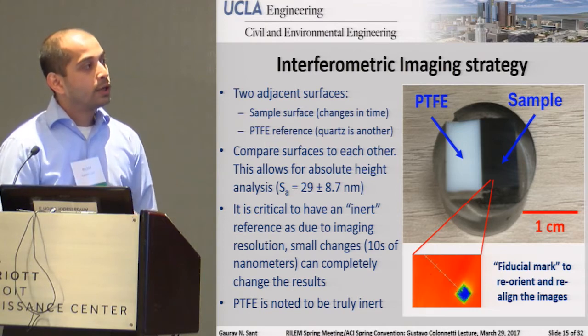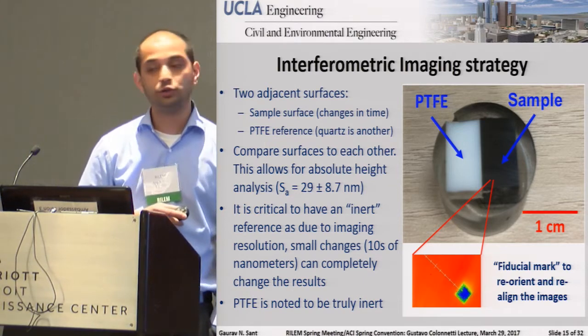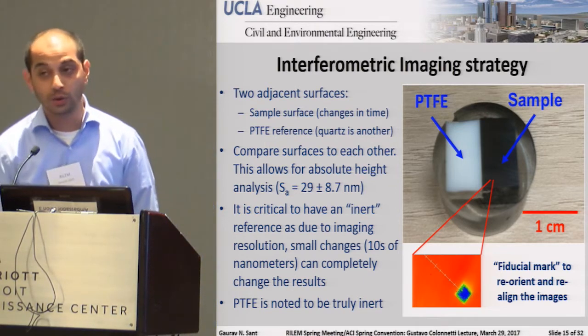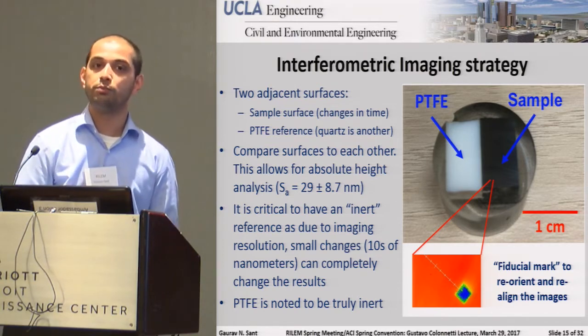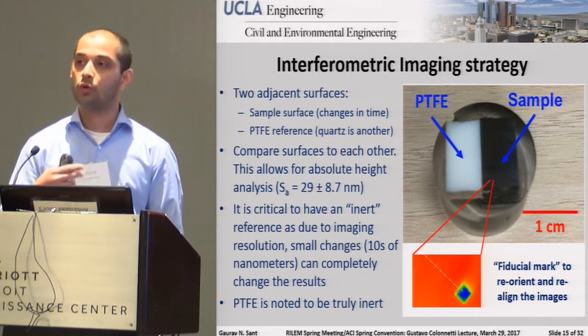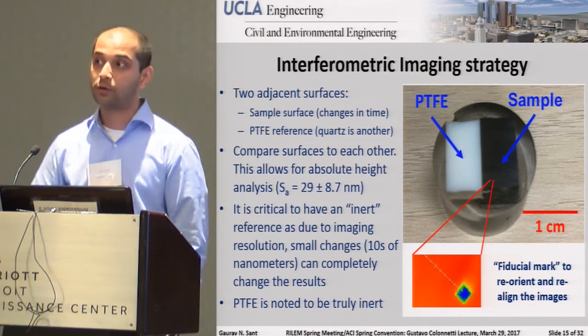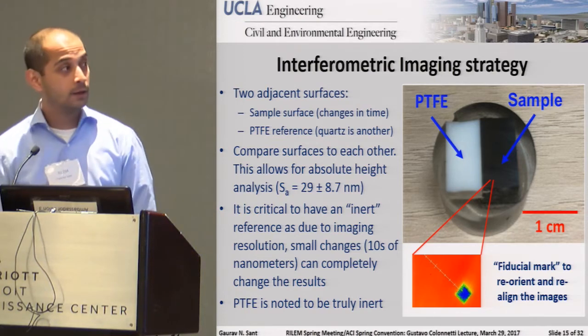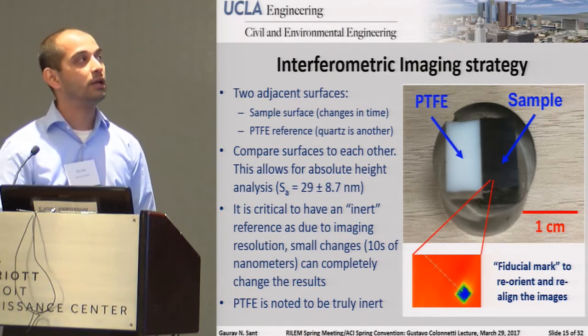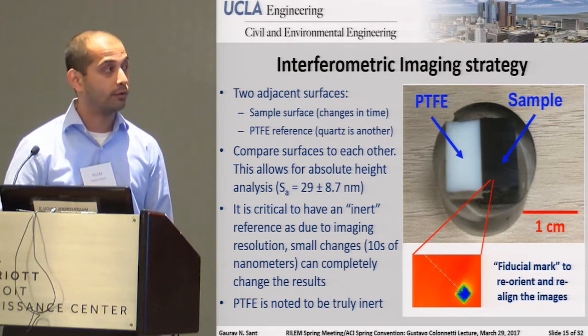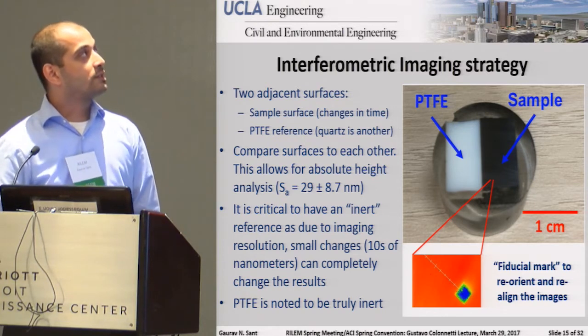When these samples are mounted, you, of course, want to have some sort of a fiducial mark on them, but you can also use what are known as kinematic stages. So these things will do positioning to be able to reposition samples over and over again to within about 1 micron, so to speak. So you can do really, really very repeatable imaging of the same areas over and over and over again. So what does this really look like?